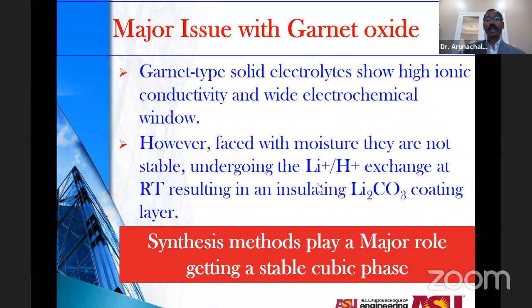This material certainly has a relatively high lithium ion conductivity along with a wider electrochemical window. That means this material has the potential to be combined with high voltage, or 5 volt, cathode materials, to also target higher energy density per kilogram.